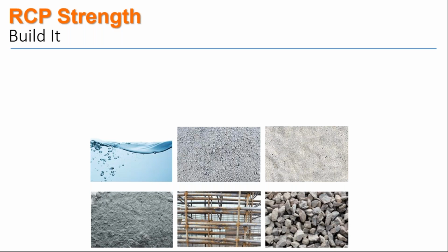So we use water, cement, sand, aggregate, reinforcing steel, and additional cementitious materials, which can help to increase the durability of the concrete. In many cases, these additional cementitious materials are actually waste products from other industries. We can add fly ash from coal-fired power plants, blast furnace slag from steel production, or silica fume from the production of silicon alloy. Incorporating those materials into the mix helps to conserve natural resources. We're not using as much cement, and it reduces the overall energy needed to produce the concrete.